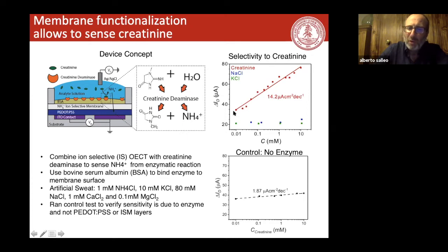So here's the result of the experiment as a function of the concentration of creatinine. You get a calibration curve, and so you can measure the concentration of creatinine, in fact, by measuring the concentration of ammonia with this type of device. And if you have no enzyme, you actually get no response to the concentration of creatinine. And for the interference here, sodium and potassium don't really do anything because we have our ammonia ion selective membrane that is always sitting on top of the PEDOT:PSS.